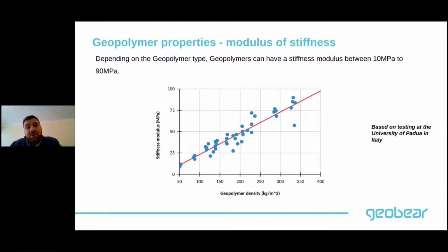Also, another important property of geopolymers is that, again, depending on the type of the geopolymer, geopolymers can have a stiffness modulus somewhere between 10 MPa all the way to 90 MPa. Yes, it is true geopolymers can have quite high compressive strength, but at the same time, the geopolymer composition is not too stiff in that sense. It has a stiffness range similar to natural soils.